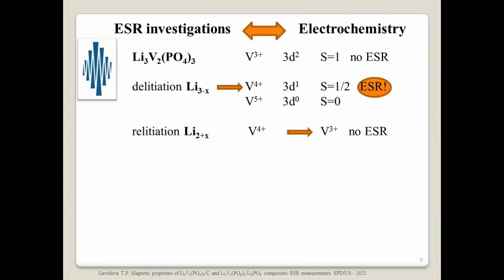How can we use ESR measurements? If we look at the chemical formula of the starting compound, we can see that in the case of a high quality sample and full stoichiometry, vanadium ions should have the valence state of 3+. In this case, they should have spin 1 and absolutely no ESR signal.